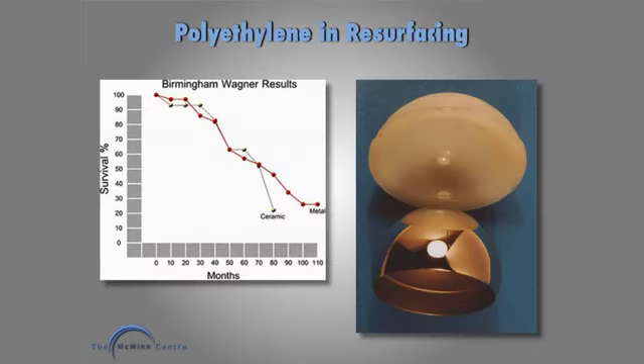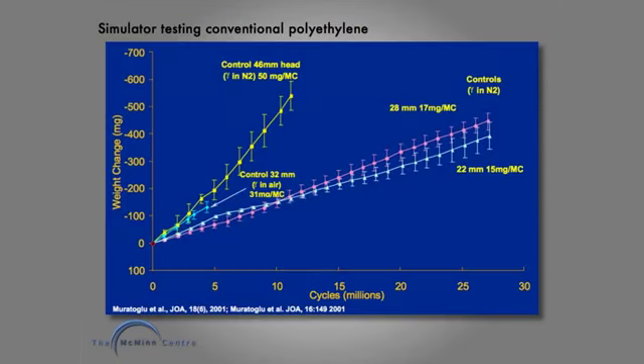Polyethylene has been tried in the past, in the 1970s and 1980s, but this was conventional polyethylene, and with both a ceramic on polyethylene and a metal on polyethylene articulation, we had high failure rates, with 50% failure rate at 6 years in both these types of joint. But I stress, this is conventional polyethylene, and it does very badly with large head size. Here's some simulator science that shows that clearly.